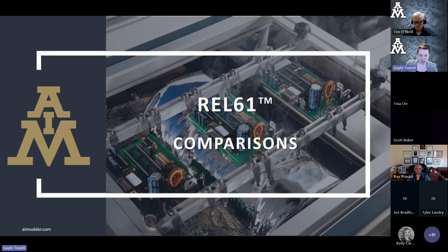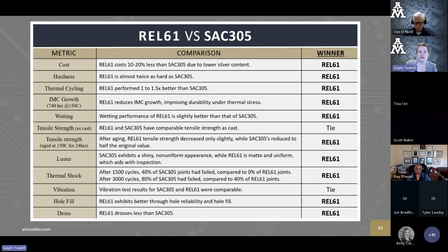So these are just some simple, quick summary comparisons of how this alloy performs versus other common alloys in its category. So versus SAC305, again, it just performs better on almost everything. It costs less, it's harder, it performs better in thermal cycling. The intermetallic growth is slightly reduced, which improves its durability under stress. Wetting performance is a little bit better. Tensile strength as cast is similar, but after aging, REL61 is better.